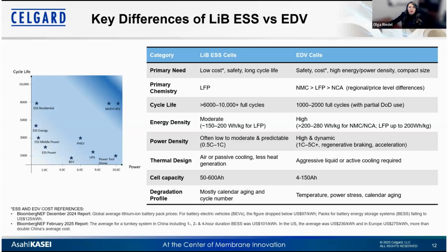In terms of long cycle life, most ESS applications require a cycle life of about 6,000 to over 10,000 full cycles, while normal EDV cells only require about 1,000 to 2,000 full cycles with only partial depths of discharge. The energy density of ESS cells is usually moderate because nowadays a lot of systems actually use LFP. But the power density is also mostly moderate.